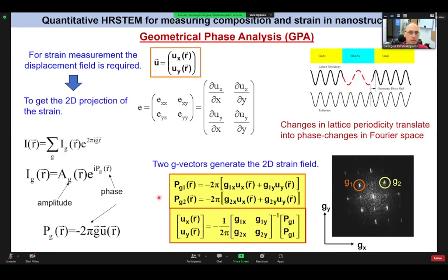Just to say, for the sake of completeness, that both with peak finding and with geometrical phase analysis, what we want to find is the displacement field. So this is the displacement field. Of course, we are talking about images. Images are two-dimensional projections of the three-dimensional crystal. So you can find the two-dimensional projection of the displacement field. This means the deviations of the atoms from their normal position.